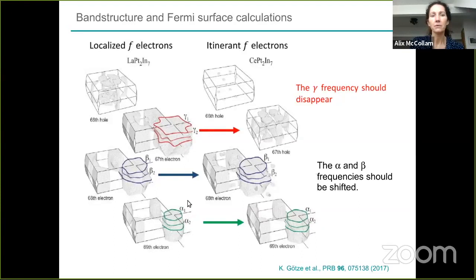So these are calculations for a localized system. So it's lanthanum platinum 2 indium 7. Lanthanum has no f-electrons, so this gives you a localized picture. Cerium platinum 2 indium 7, this is calculated with the f-electrons as part of the Fermi surface. So itinerant f-electrons, this would be a Kondo scenario, or any scenario in which the f-electron becomes part of the Fermi volume.